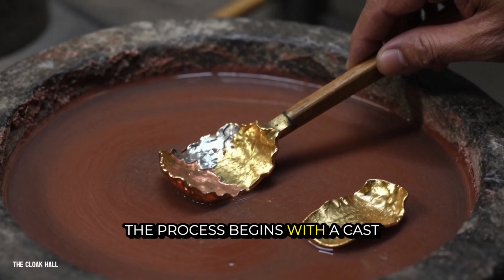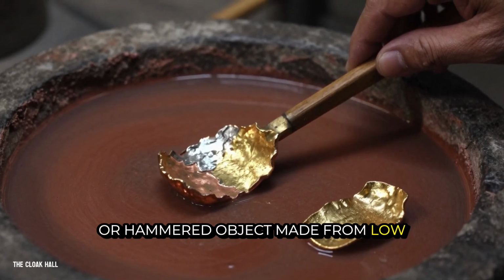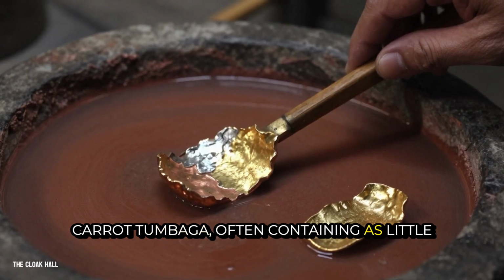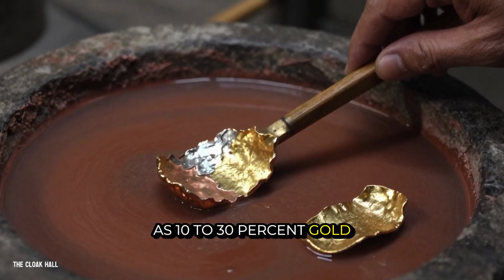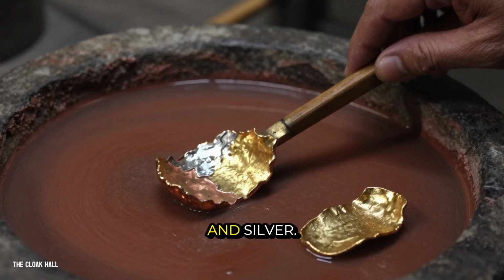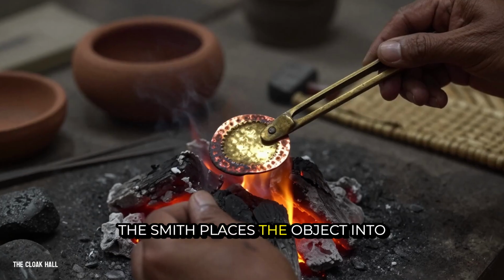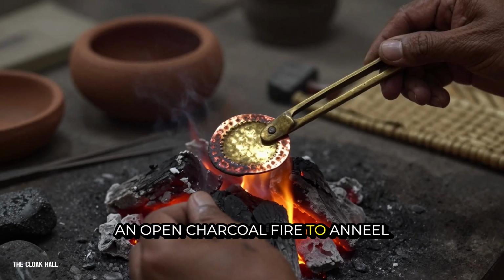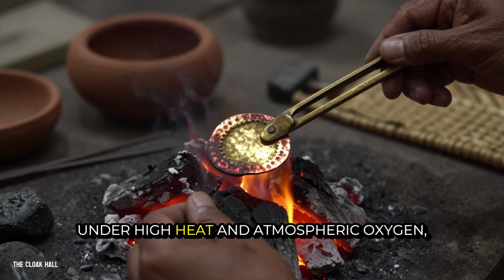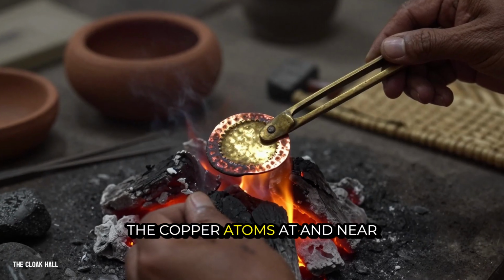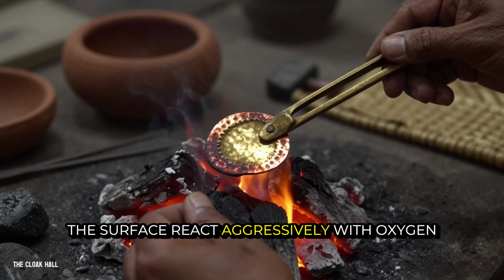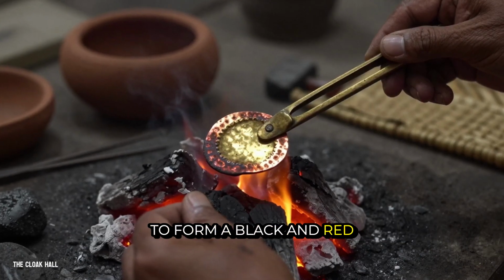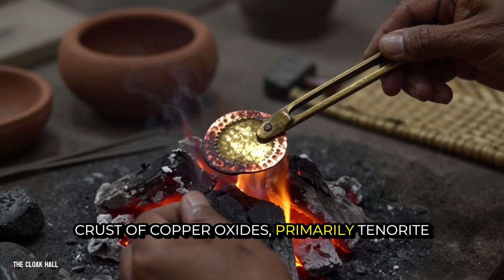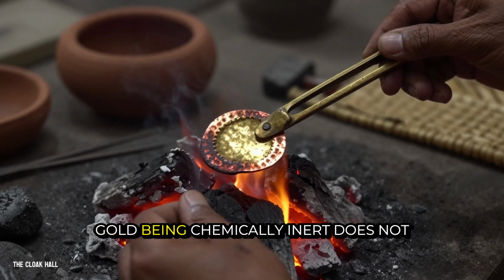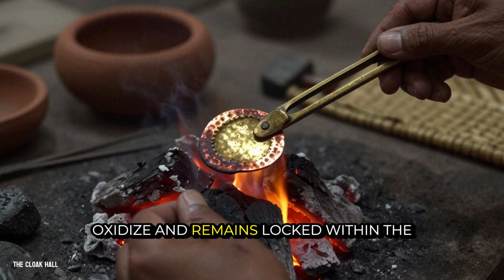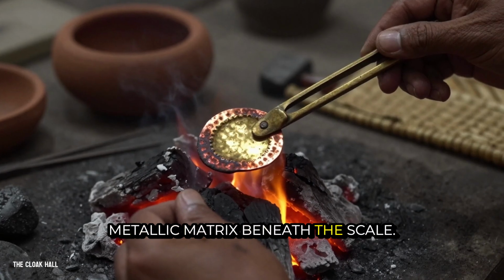The process begins with a cast or hammered object made from low-carat tumbaga, often containing as little as 10 to 30% gold, with the remainder consisting of copper and silver. The smith places the object into an open charcoal fire to anneal the metal. Under high heat and atmospheric oxygen, the copper atoms at and near the surface react aggressively with oxygen to form a black and red crust of copper oxides, primarily tenorite and cuprite. Gold, being chemically inert, does not oxidize and remains locked within the metallic matrix beneath the scale.